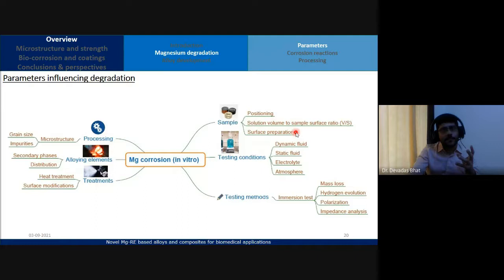Then comes the surface preparation. Whether you're going to perform the test in a dynamic fluid, whether your fluid is static, what is the atmosphere that you have in the testing condition. So if we want to mimic the body conditions, we go for 37 degrees Celsius body temperature and 5% carbon dioxide atmosphere, right? And then the electrolyte. The electrolyte that you choose, how is it close to the body plasma or the blood plasma, you know? The pH value and the concentration, all these.